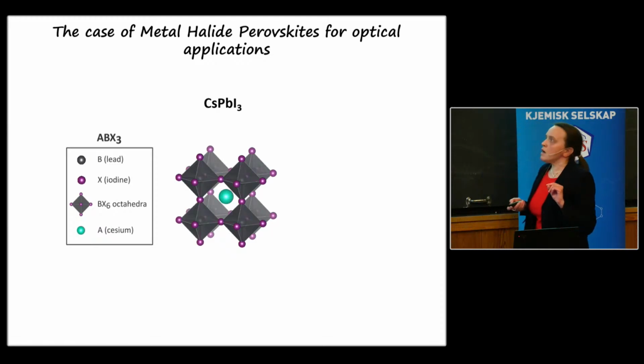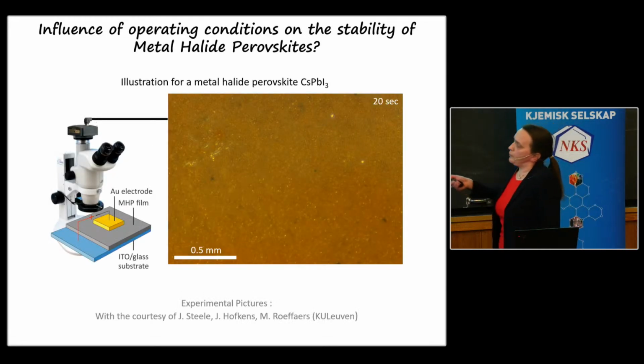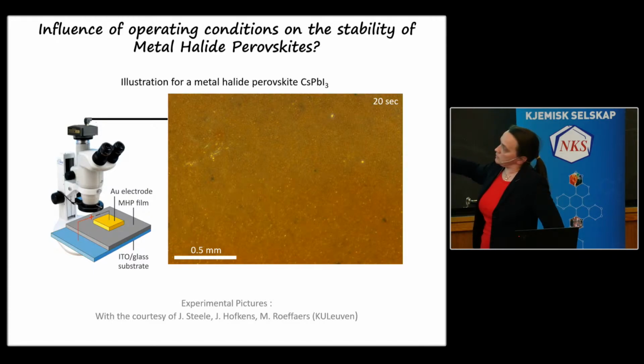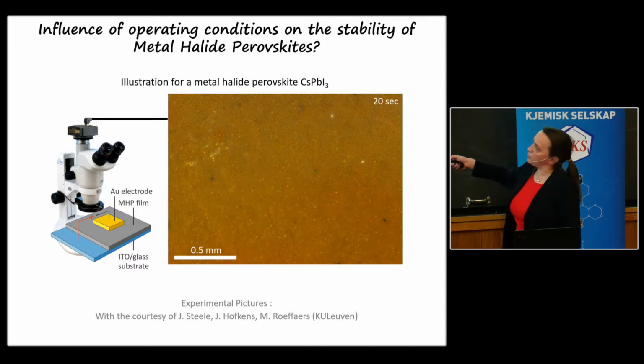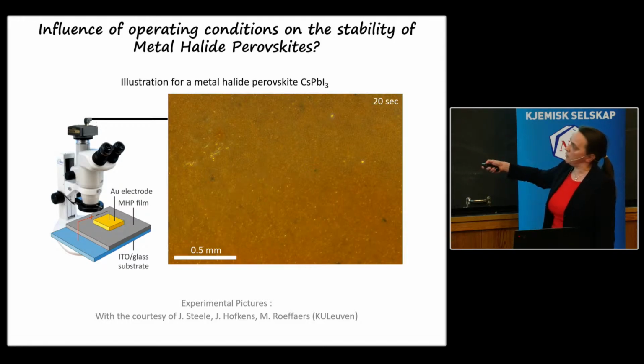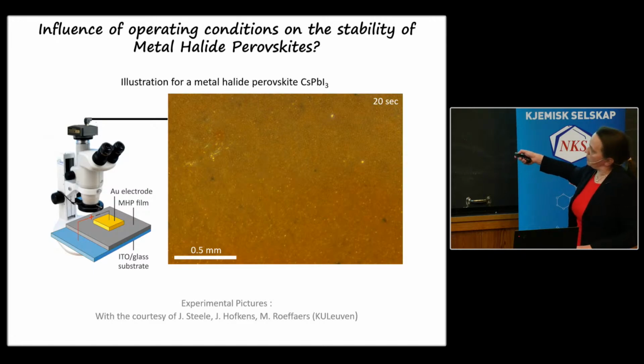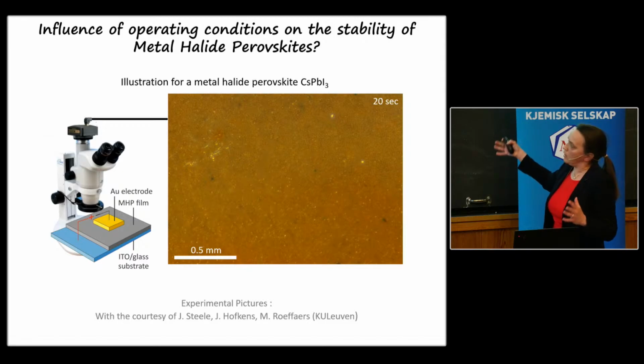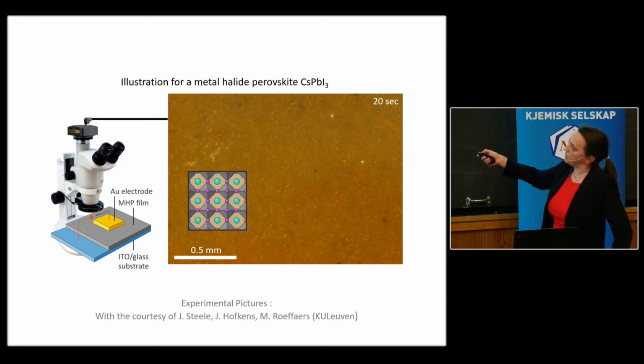Now, what did our experimental colleagues do? They deposited this material. This yellow layer here is the metal halide perovskite, which is deposited as a thin film on an underlying substrate. This is the material which has the right optical function, and a spectroscopic technique is used. So we start from this material where everything is right in place, with the octahedrons well connected.